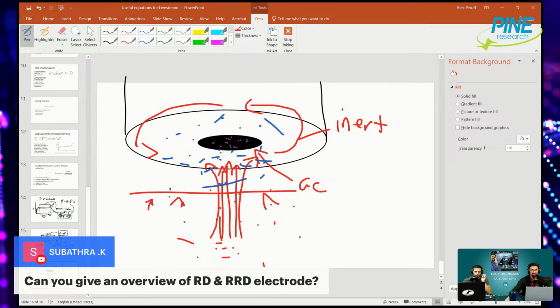But when you rotate the electrode, you're overcoming this diffusion layer thickness. In fact, you're actually able to control the diffusion layer thickness as a function of the rotation rate. This is something that you cannot do in a stationary electrode configuration. So a lot of scientists figured out stuff a long time ago.